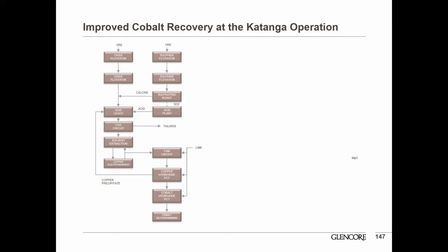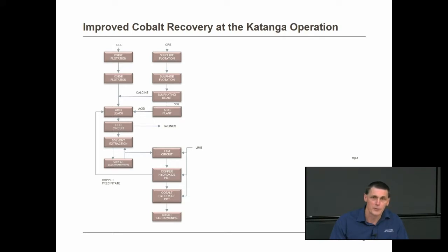I'll speak to one of the operations that we're currently upgrading in the Democratic Republic of the Congo at the moment. This is our Katanga operation. On the left-hand side of the screen you can see the existing flow sheet that we had at Katanga, where we had a combined oxide and sulfide flotation circuit producing copper as SXEW metal and producing cobalt as a cobalt hydroxide product. We're expanding that operation at the moment from about 120 to about 350,000 tonnes of copper, and because of the value of cobalt we're looking to improve cobalt and copper recovery.